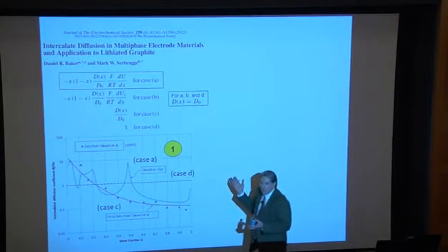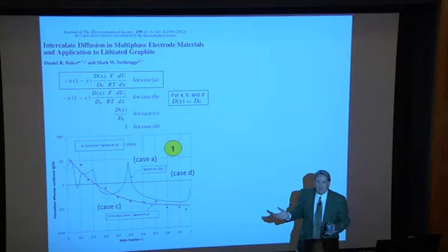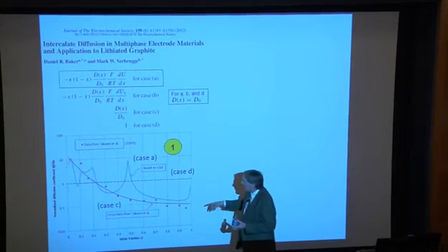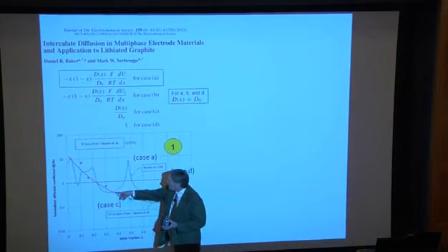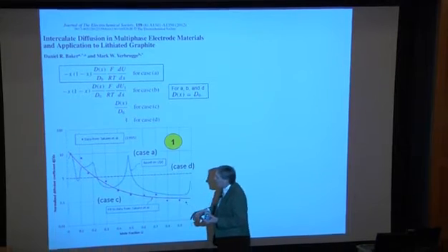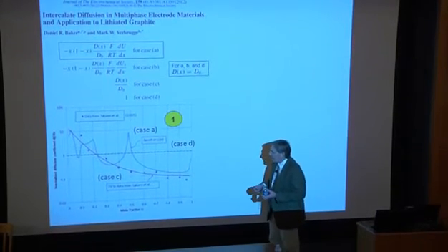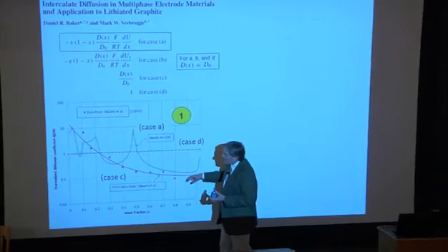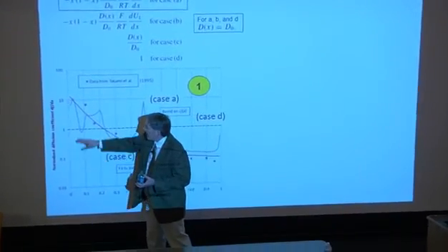And they were sort of bizarre looking. I hadn't seen anything like this myself. And so that was kind of worrisome. There were people out in the literature who were fitting diffusion coefficients simply to existing data by, in this case, Takami et al. And you can see the diffusion coefficients varied by 2 orders of magnitude.